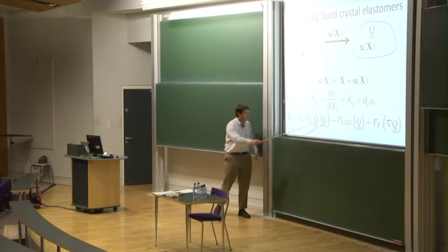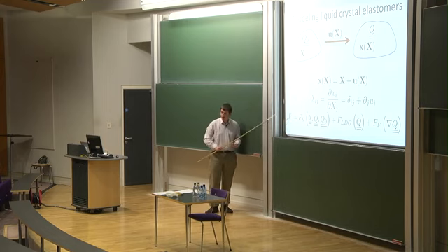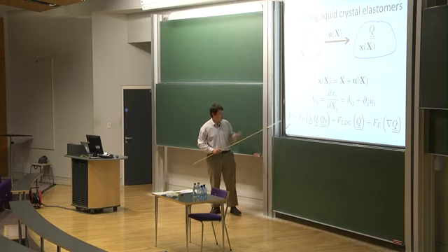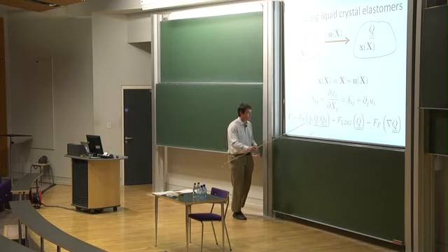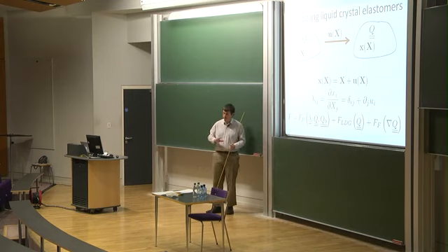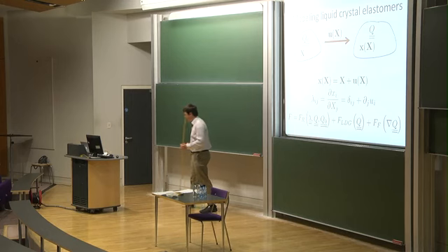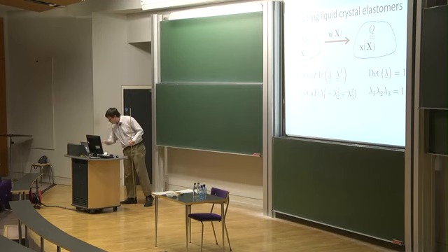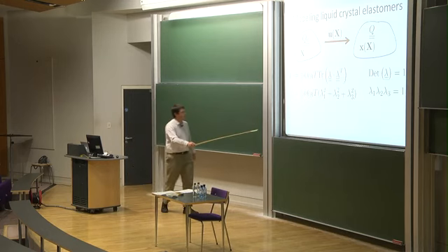And so all we're going to have left is my polymer part of the energy, but modulo the consideration that because we know about these other parts, the magnitude of Q is no longer a free variable, but the direction of the nematic order is still something which can couple to the rubber elasticity. Okay, so we've reduced our problem from three components just to one.